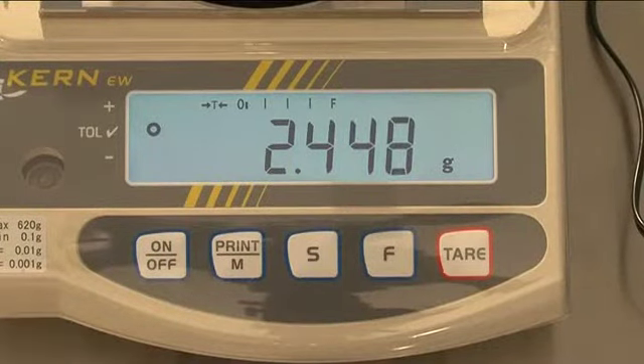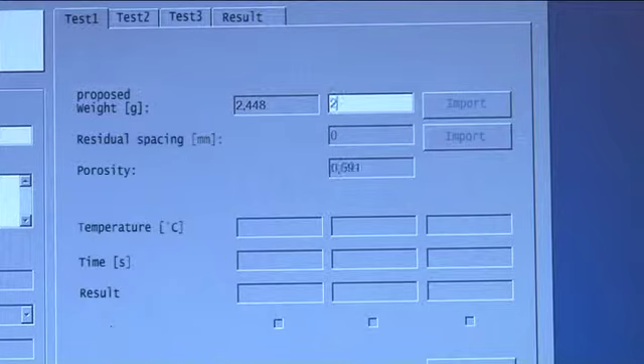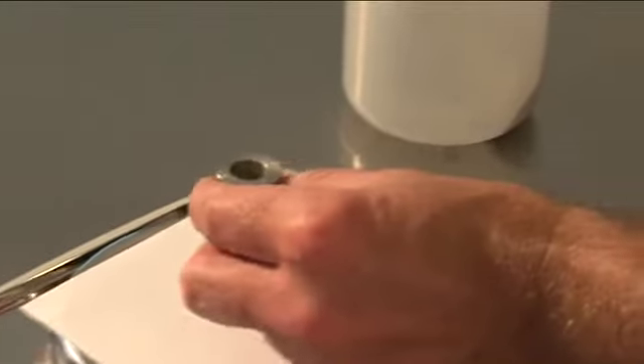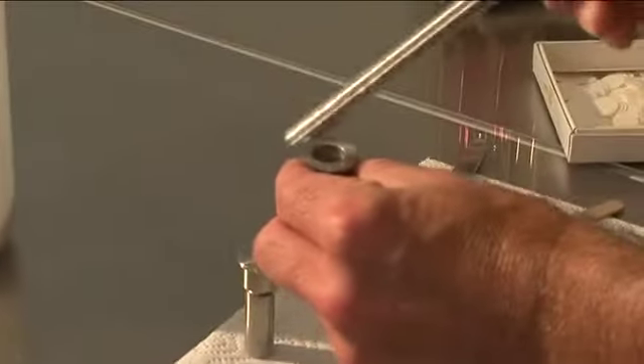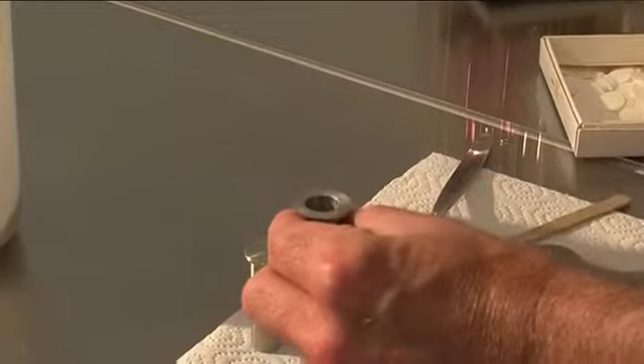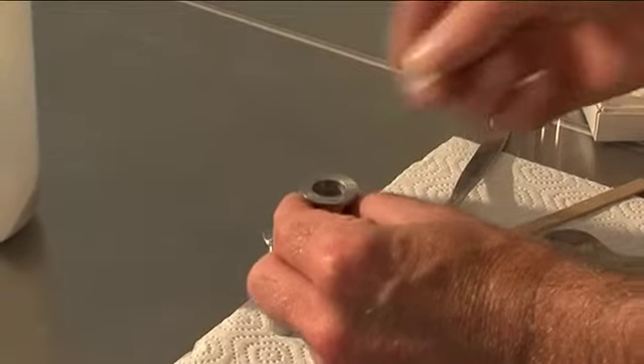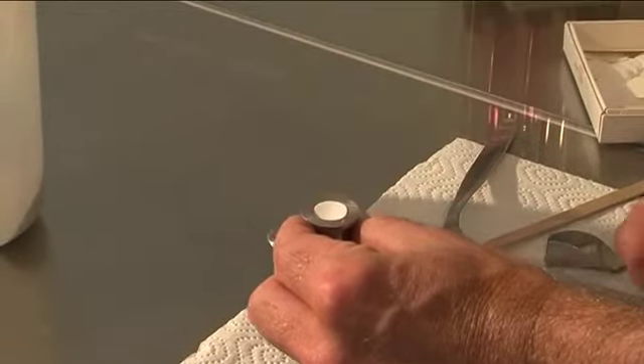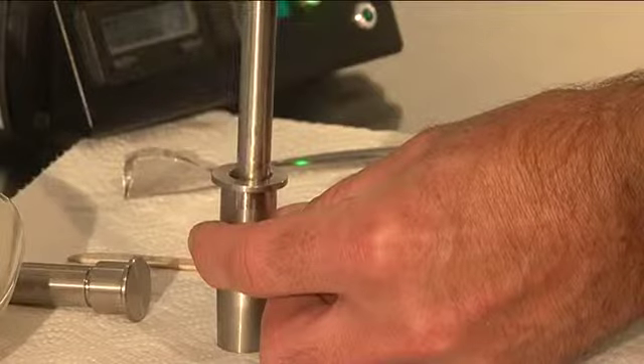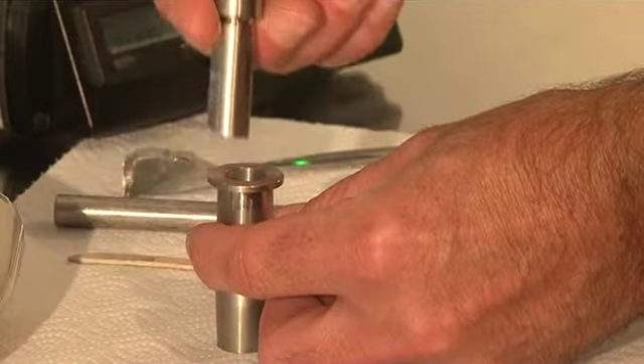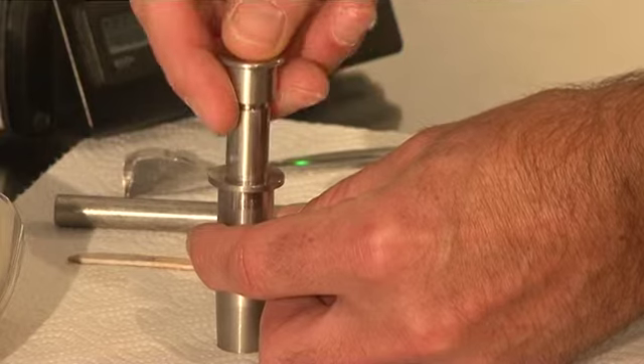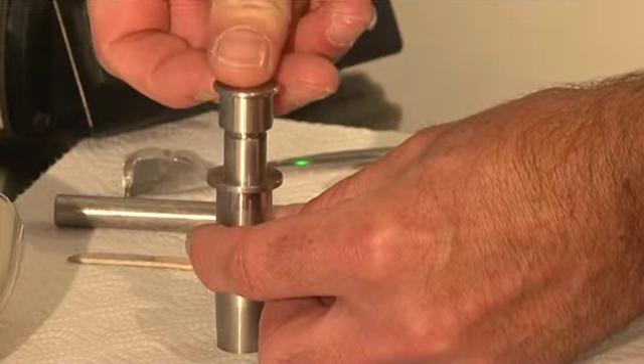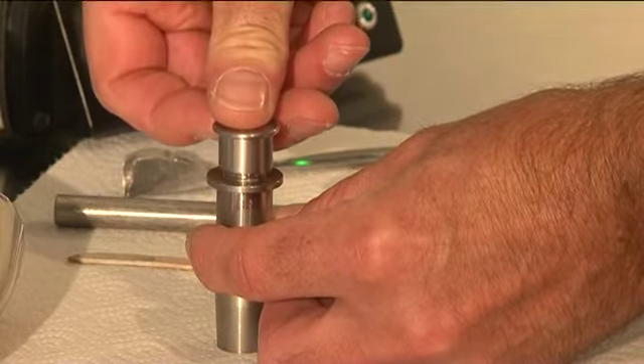Enter the weighed quantity of powder in the field. The powder bed is leveled by lightly tapping the cell wall. A second filter paper is placed on the leveled surface area. In order to compact the powder bed gently but firmly, press the plunger onto the bed so that the lower face is in contact with the upper edge of the cell.